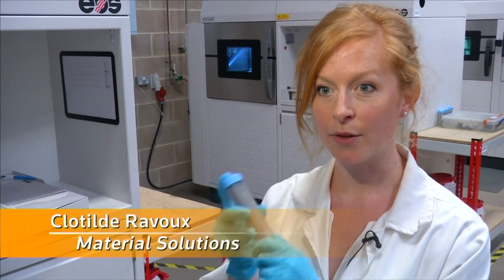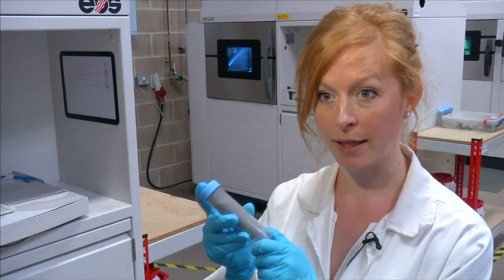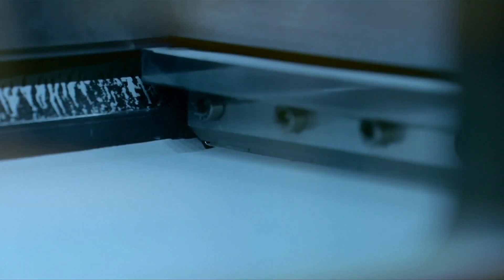This is the nickel superalloy powder. This metallic powder is deposited in 20-micron layer thickness and then the laser melts the part. Ultra-thin layers are added one by one, building up the component.